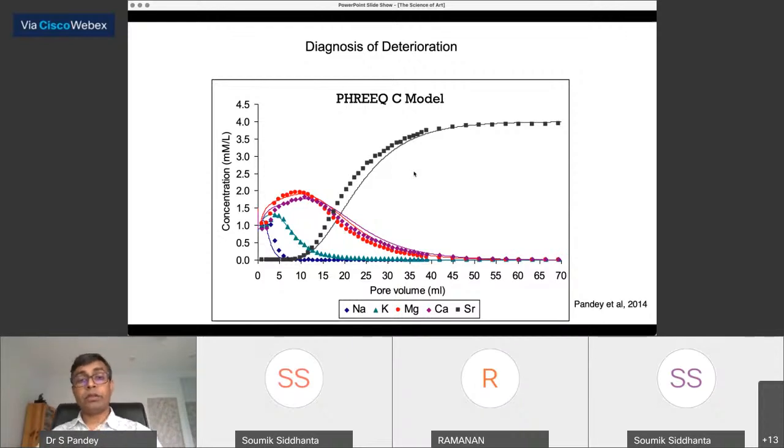Both of these have different RH equilibrium conditions. And when the RH fluctuations happen, it will crystallize, transform from one phase to the other, and back to the previous one. And therefore, these would lead to much more damage to cultural heritage, because the transformation is happening multiple times.